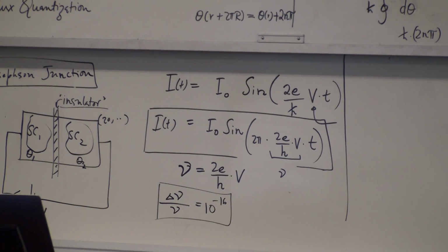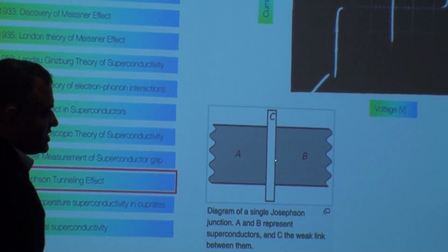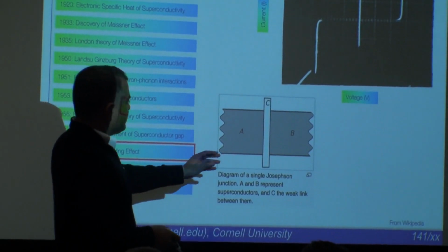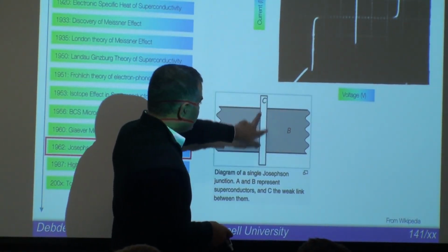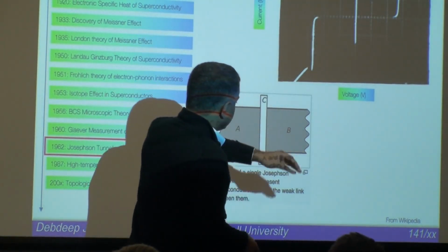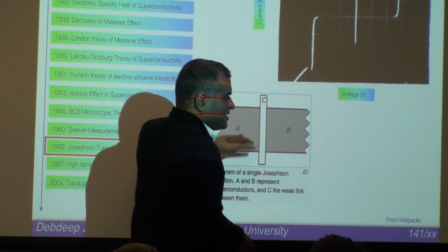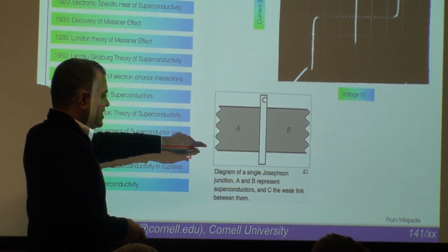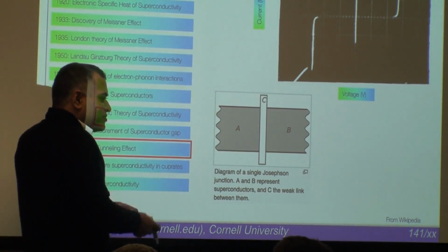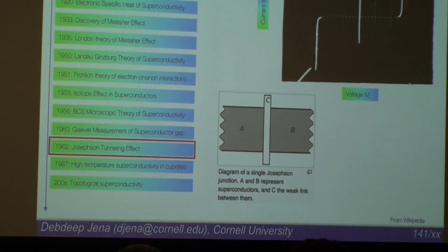Yeah, so the problem would be, it is mostly independent, but as long as you are able to make the Cooper-Pairs tunnel, that part of it is the tricky part. Meaning if this is too thick, or if the barrier is too high, or there are shorts of normal metal through the insulator, anything that messes that up has a possibility of messing things up. The Josephson junction will still be going on, but it will be buried under some other signals. You can't extract it now. That's the issue typically.